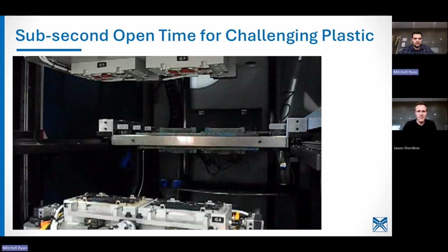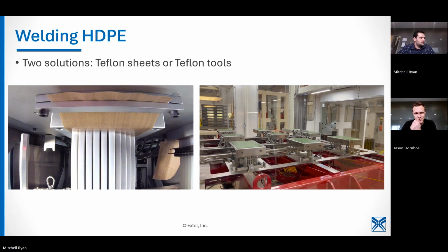So an example of that, I'm going to grab control from Mitch here a second, is back when we were looking at that Teflon tools. So this on the right here is the tool, and there's actually heaters inside of that tool, and then we actually have heat isolators that are making sure that the carriage itself remains as cool as possible. So it depends on the situation whether we want to put the heaters in the tooling or whether we want to put them in the platen, but we can do either.